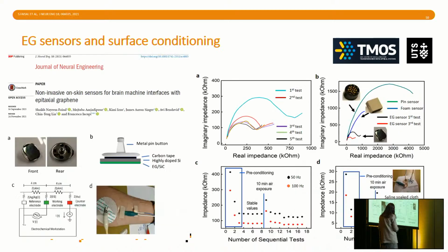Now this is where graphene can do something different. Graphene is not a conventional thin film, it is a 2D film, and we know we can intercalate graphene. And intercalated graphene can have quite a good stability. So what we were able to show is that by using graphene directly in contact, well, first of all, it's biocompatible. Both graphene and silicon carbide are biocompatible, which is great. So you can keep it for a long time in contact with the skin with no noxious reactions.